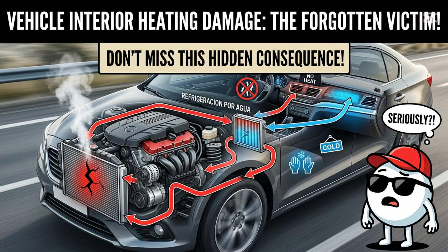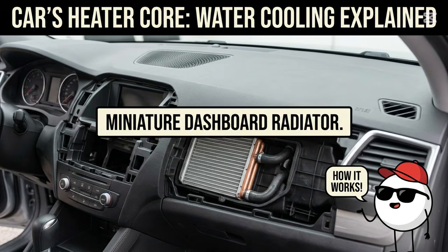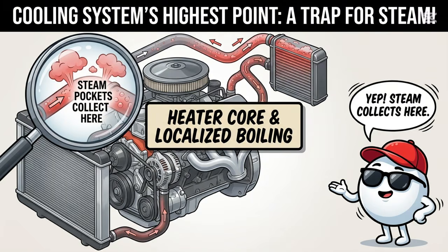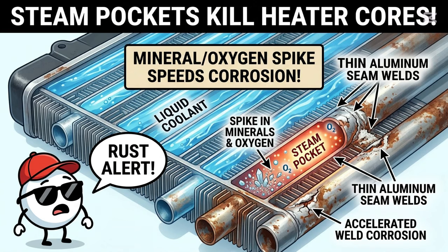There's a secondary casualty in all of this that almost never comes up when people talk about cooling system damage, and that's your vehicle's interior heating and ventilation system. Your car's heater core is, mechanically speaking, a miniature radiator hidden deep inside the dashboard, built from ultra-thin aluminum or copper tubing designed to pull heat off the engine coolant and blow it into the cabin airstream. Because of how it's plumbed into the cooling loop, the heater core often sits at one of the highest physical points in the entire system. And that matters because steam pockets created by localized microboiling naturally rise and tend to collect right there. When steam pockets replace liquid coolant inside the heater core matrix, the local concentration of dissolved minerals and dissolved oxygen spikes dramatically in that trapped pocket, far higher than in the rest of the system, which accelerates corrosion specifically along the thin aluminum seam welds holding the core together.